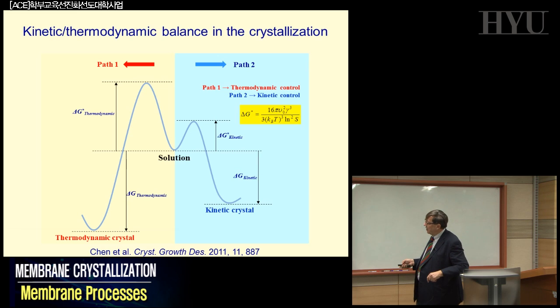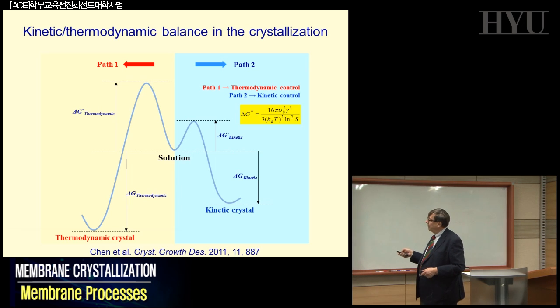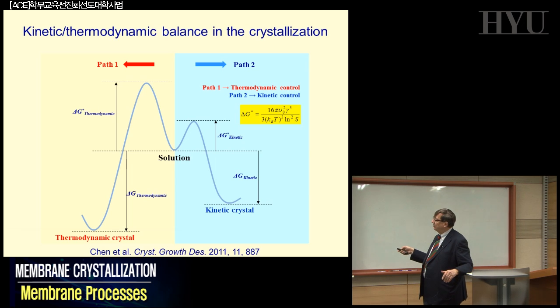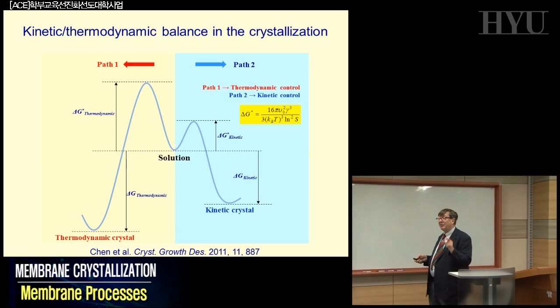When you move from one species to the final one, as you know, you have to overcome barriers that are called the activation energy of your system. And if everything is regular, at the end you have a crystal that is thermodynamically stable, the one that is normally formed in terms of potential energy of the reactant compared to the product of your reaction. And that's exactly what happens. But in the meantime, we have a metastable phase in the crystal formation. The metastable phase, normally, you don't take too much care of, because the metastable phases are metastable. So slowly they appear, but they disappear.